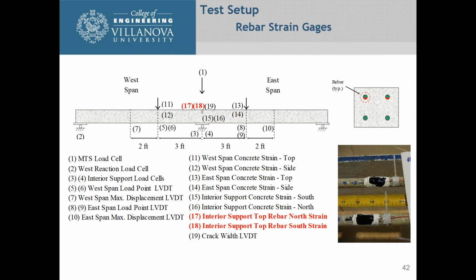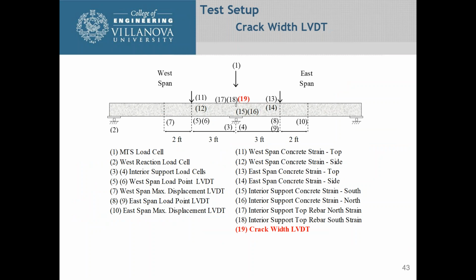Additionally, we put strain gauges on the GFRP bars on the top bars, since those were going to be in tension. This ended up being not working out too well because either the bonding that we were doing or there was some issue with the wires disconnecting, because I would have to say on half of them we lost signal. And the last thing we had was an LVDT at the center support on the top, calculating out what the crack width was.